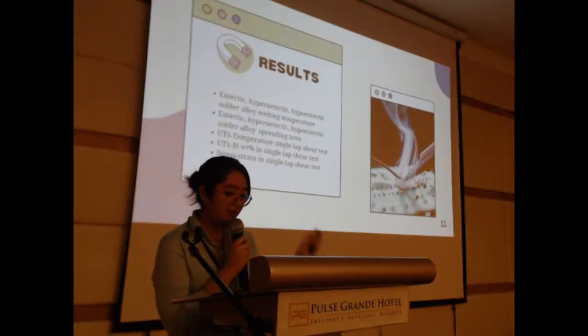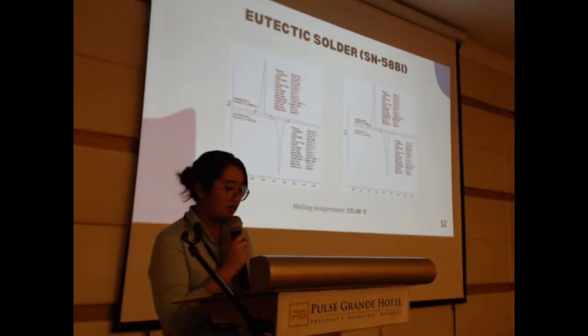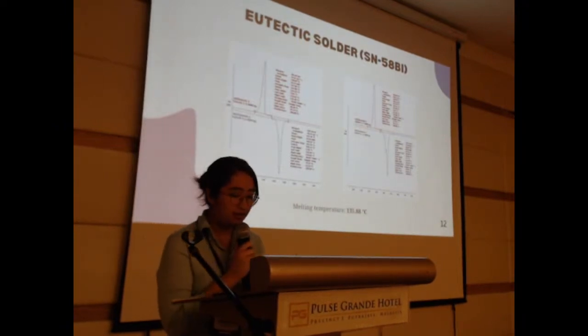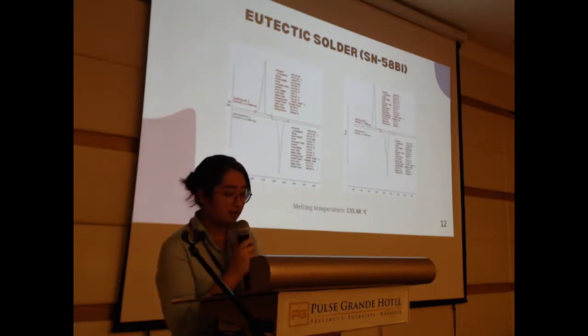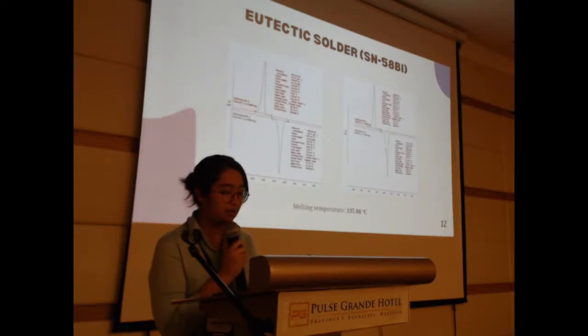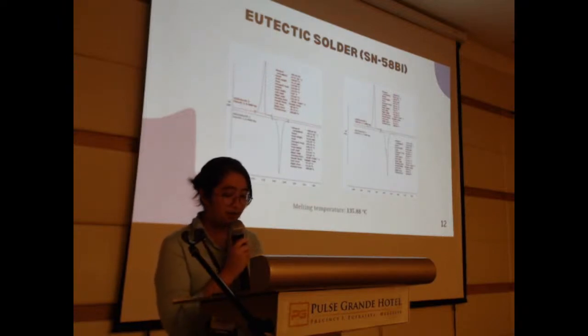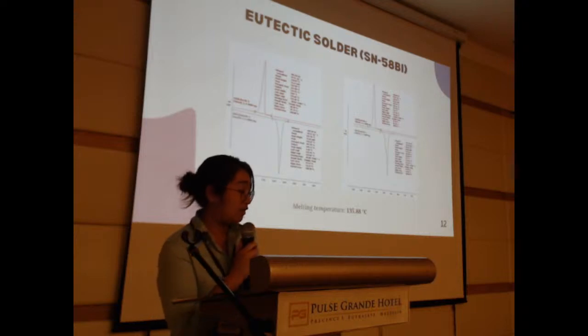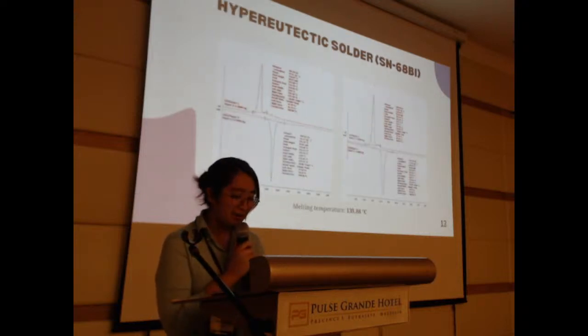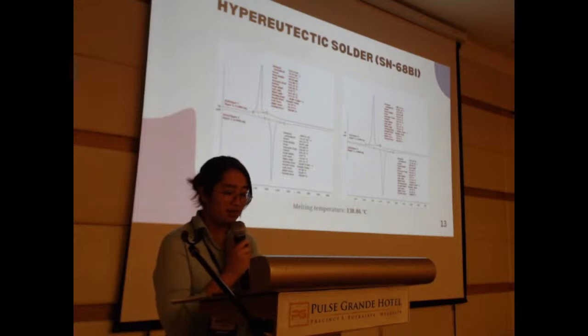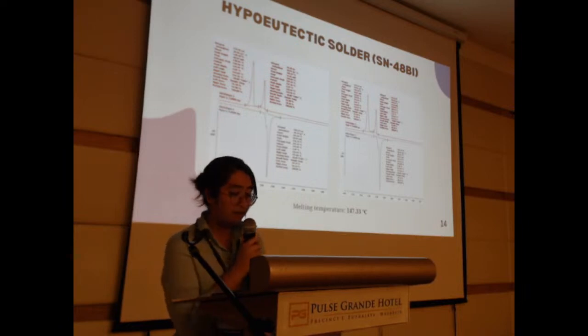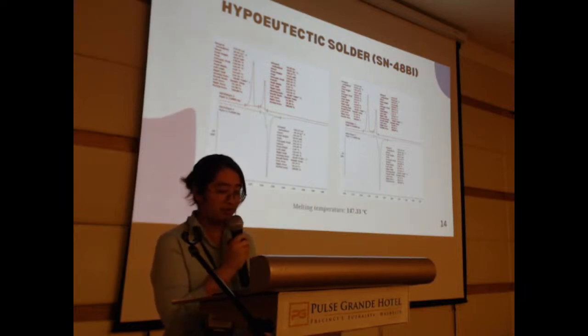So onto the results. As you can see on this first diagram, these are the phase diagrams from the DSC machine. I have tested 2 times for each composition, just to get the average. So for 58% bismuth, the melting temperature is about 135.88 degrees, sorry. And for 68% bismuth it is about 138.88 degrees Celsius, and for 48% bismuth it is 147.33 degrees Celsius.